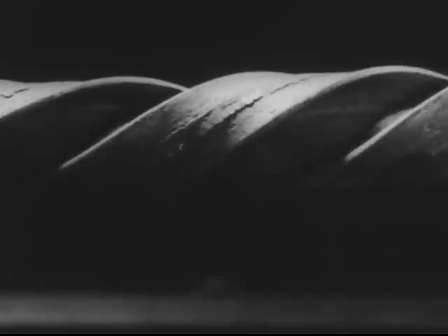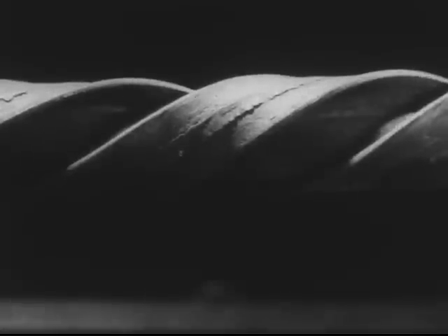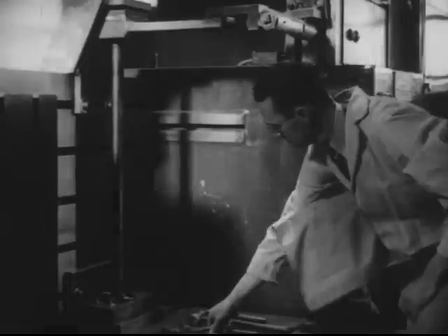As easily as this housewife wrings out a dish towel, this machine twists up a front axle. The axle, which is made of heat-treated manganese alloy steel, is twisted around and around again for 9 complete turns without a break. This is impressive proof of the toughness of this vital part.